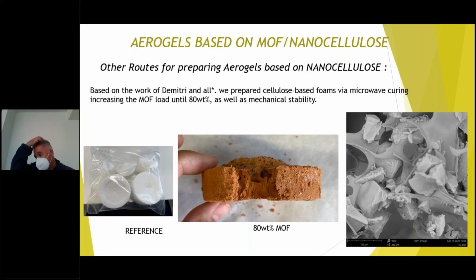Based on initial work from Professor Dimitri, we made several modifications of the process, including the lyophilization, the freeze drying process. We prepared these cellulose-based foams via microwave curing. And with this type of process, we reach up to 80% of perfectly dispersed MOF inside this nanocellulose foam structure. This is very different from what we obtained at the beginning with the impregnation process, where with difficulties we reached only 5% of MOF inside of the foam structure.